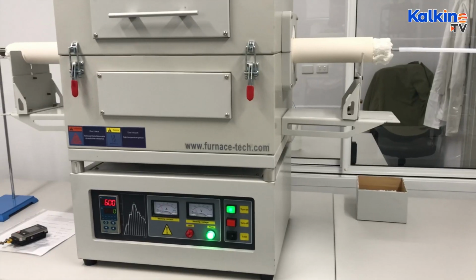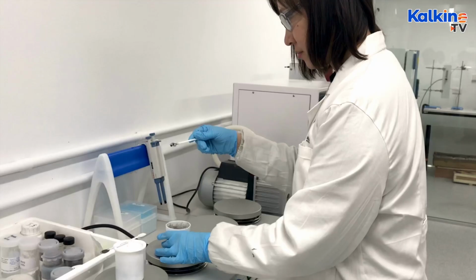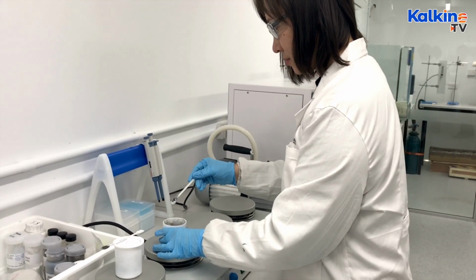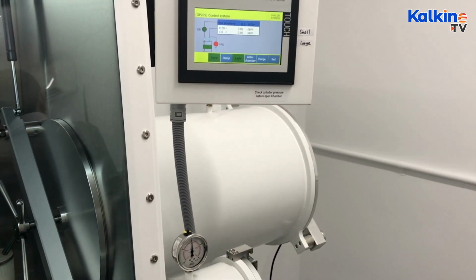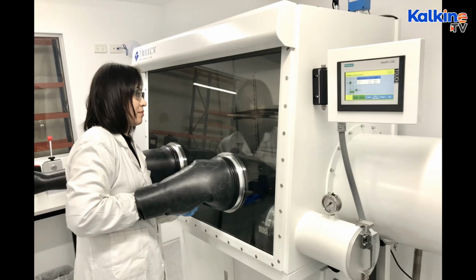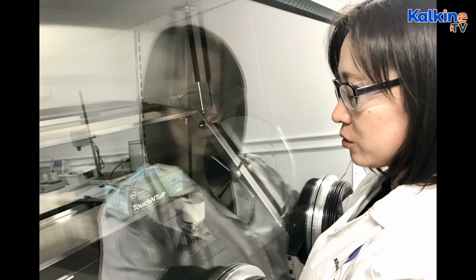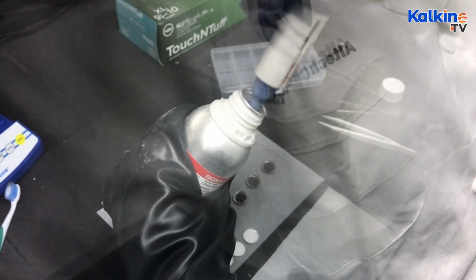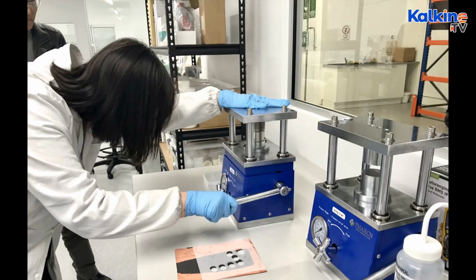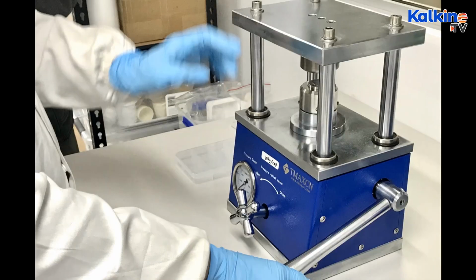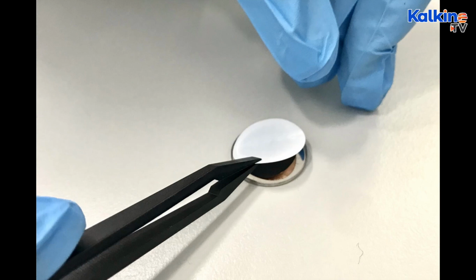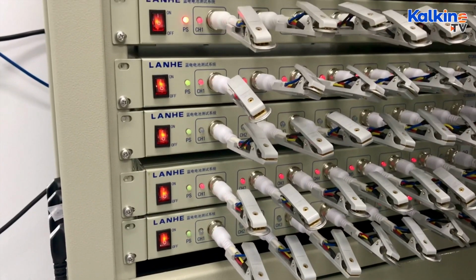Now, we've done a lot of work in our research and development laboratories, and we managed to coat our alumina around the silicon particle, a very uniform layer around the silicon and graphite particle. And we have now put it into batteries, and we've done a lot of the testing work for the performance of the batteries. What we can say is that it looks very promising. Obviously, we have to conduct more trials, but the performance so far looks very promising.